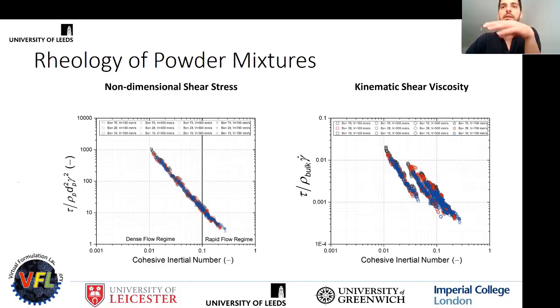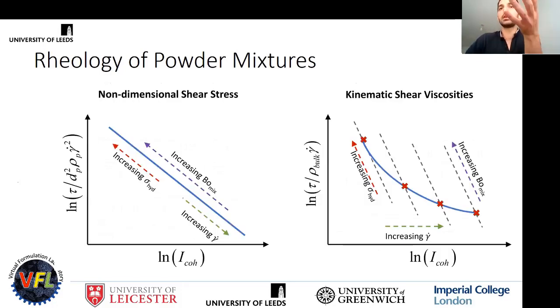So if you go next. In terms of the generic curves, on the left-hand side you see the non-dimensional shear stress, and we have a master curve where, increasing the shear rate, we are going down the slope. Increasing the hydrostatic stress, we are going up the slope. And increasing the bond number, again, we are going up the slope. And from that, we can also derive a similar curve for kinematic shear viscosity.